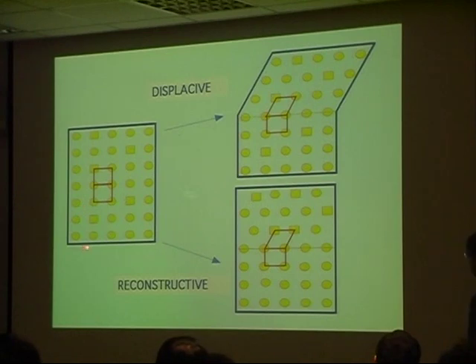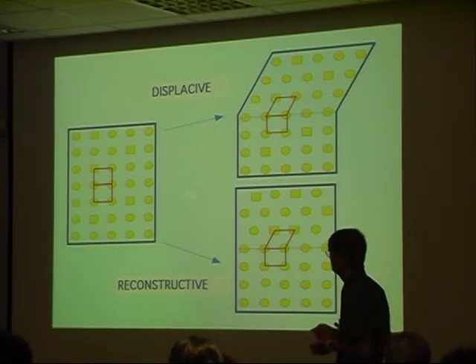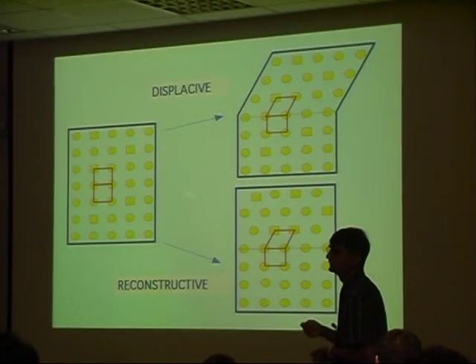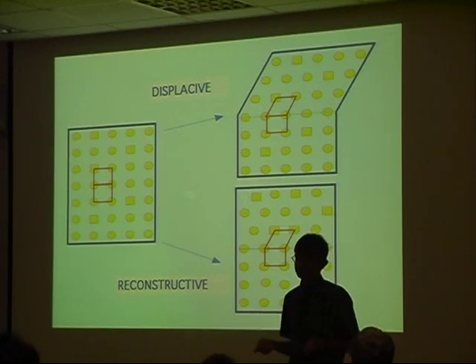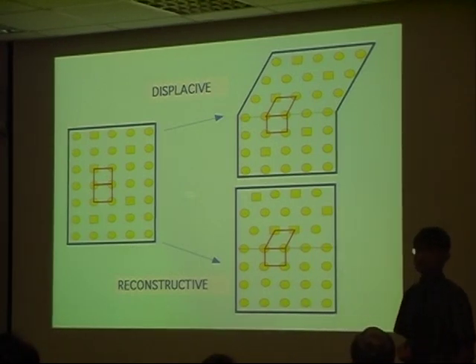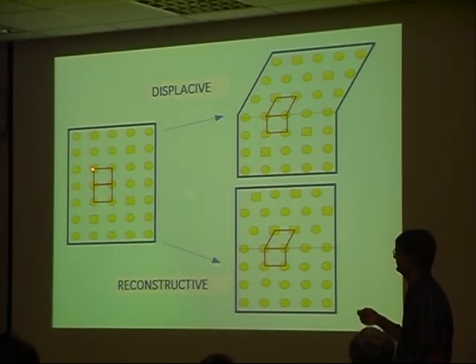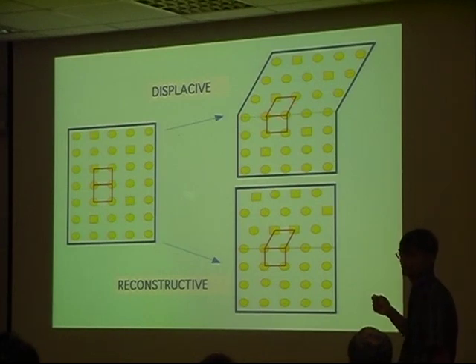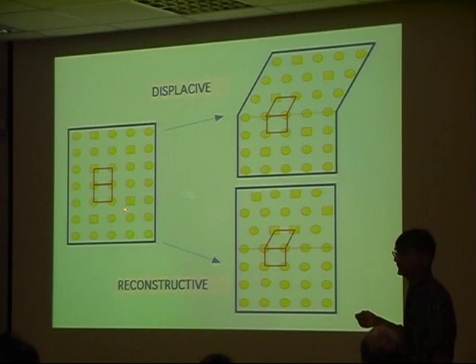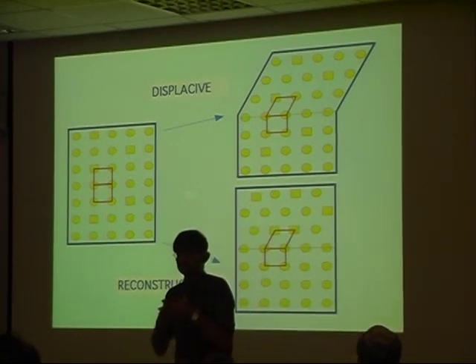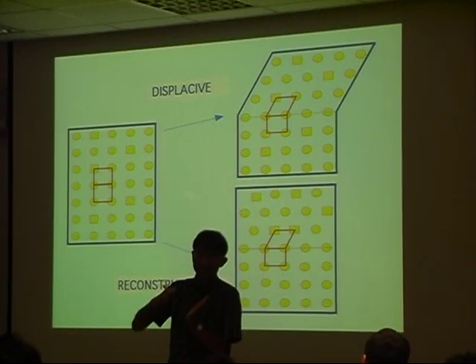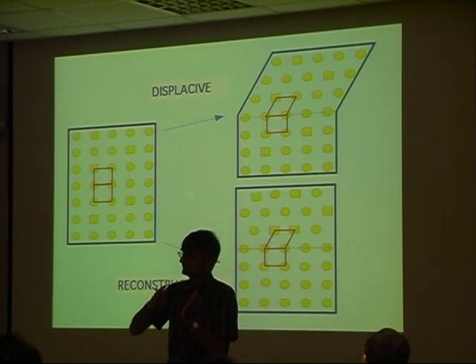I'm going to rule out mechanical alloying as a method for producing large quantities of cheap nanocrystalline metals. Let's now look at the possibility of producing large quantities by phase transformation to generate very fine structures. The steel industry has been working on this for many decades. The finer the grain size, the better. The big breakthrough happened in 1960s when microalloyed steel came about so that you could control the austenite grain size and therefore produce a finer ferrite grain size. Recently there are big projects in Japan, China, Korea on producing one micrometer or less than one micrometer ferrite grain size by deformation. In order to talk about phase transformations, I need to explain the mechanism by which a phase transformation happens because there are different kinds of phase transformations.